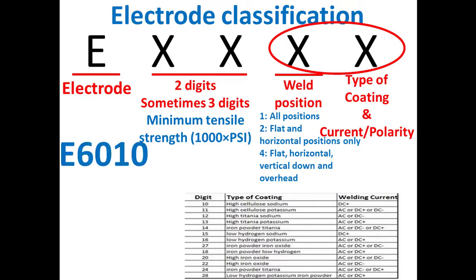Now, for example, this designation E6010 means that this is an electrode for arc welding. 60 means that the minimum tensile strength of this electrode is 60,000 psi. 1 means that this electrode can be used in all welding positions, and 10 means that the type of the coating is the high cellulose sodium, and the welding current is DC+, which means direct current reverse polarity.